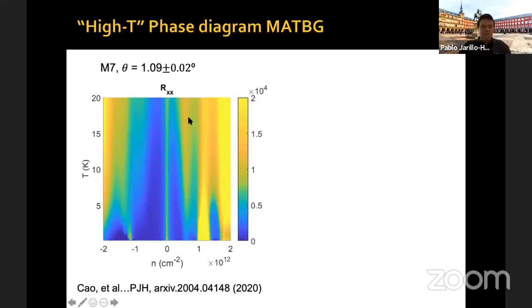So this is the phase diagram for a magic angle device, 1.09 degrees. This is temperature versus density. You can see here zero density. This is the charge neutrality point. The resistance, which I'm plotting on the color axis, has a high resistivity here at the charge neutrality point. And then you can see that interesting physics appears at 1, 2, 3 electrons per moiré unit cell, also at 2 holes per moiré unit cell.